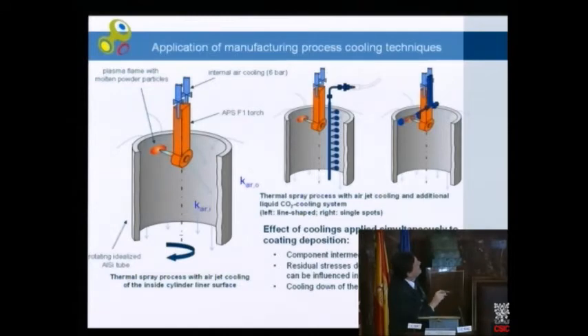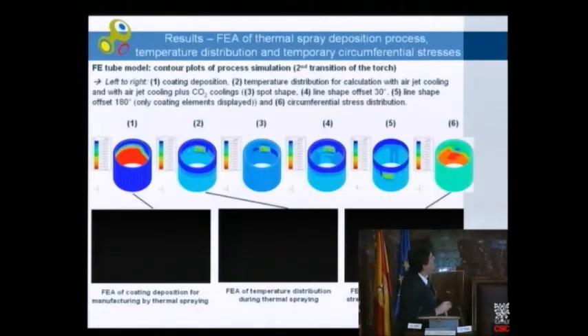So we have the compressed air plus the liquid carbon dioxide cooling. And here one of the most sophisticated simultaneous cooling systems with two cold spots, not only the hot spot, two cold spots. And just to give the beginners an idea, with a plasma jet with more than 3,000–4,000 K on the surface, we can handle it so that the substrate will not exceed a total temperature of 60 or 70 degrees C. That means the effects of this simultaneous cooling are crucial and are one of the most important tools in our hand to overcome the misfit in the original material's properties.